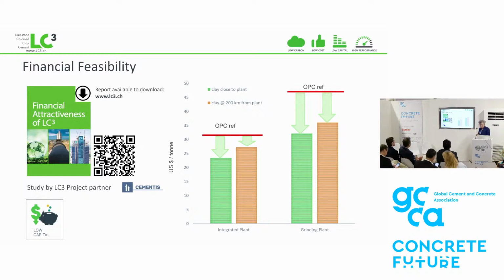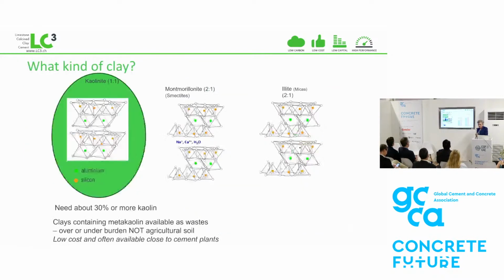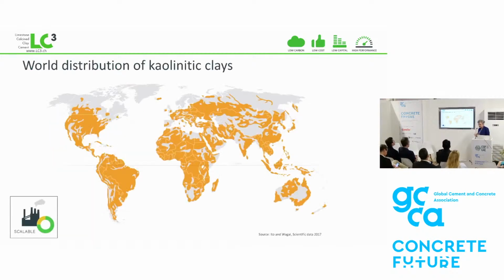This is a study we did a while ago where all the figures are in this report that can be downloaded on the website, but you can usually save compared to the OPEX production of OPC in both an integrated plant, but especially in grinding plants. Of course, the critical question is what kind of clay, and basically we need to have some of this mineral kaolinite, which is this so-called one-to-one clay, and because of this crystal structure, both the calcium and the aluminate component are available to react. And the aluminate component actually reacts with the limestone, which is why you have a synergetic effect for this coupled substitution.